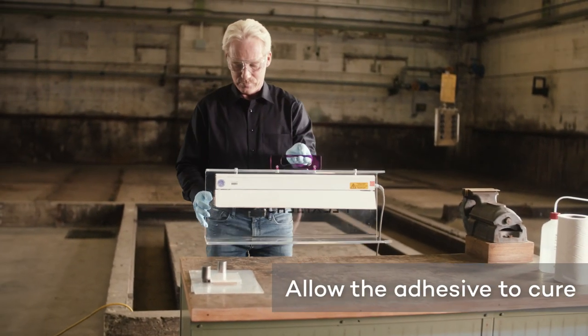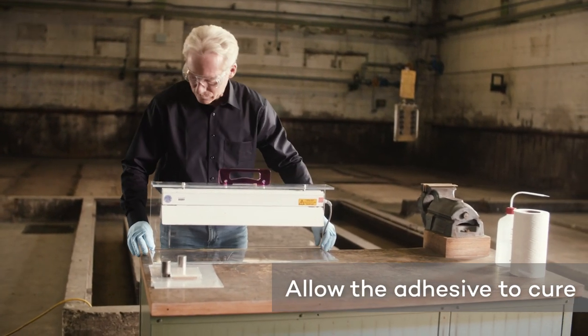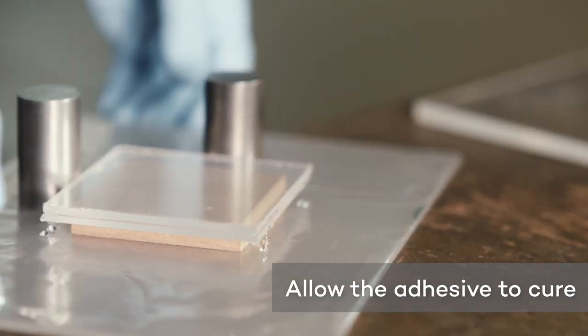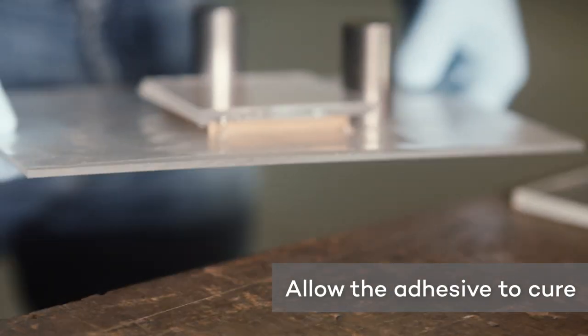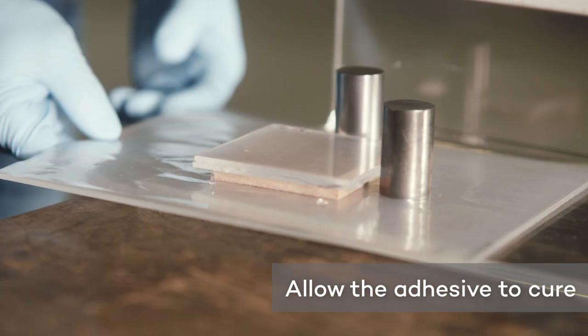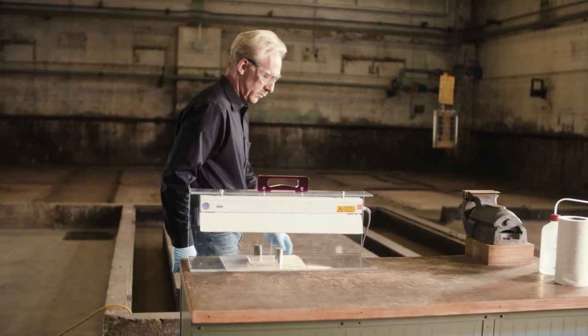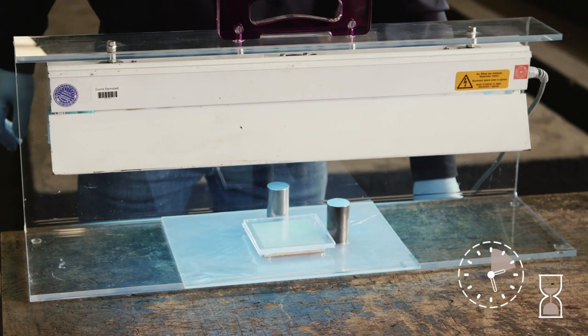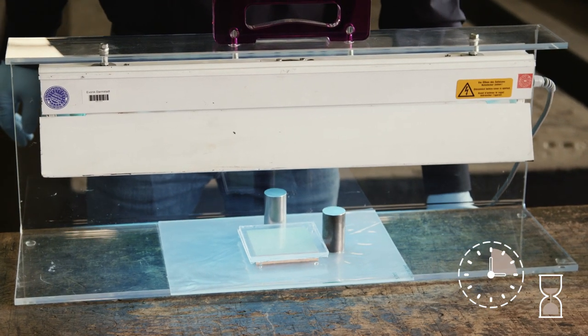Allow the adhesive to cure under daylight or UV light. The curing time is dependent on the light irradiation. You can continue processing the material after a minimum of three hours. Its final strength is reached by the next day at the earliest.